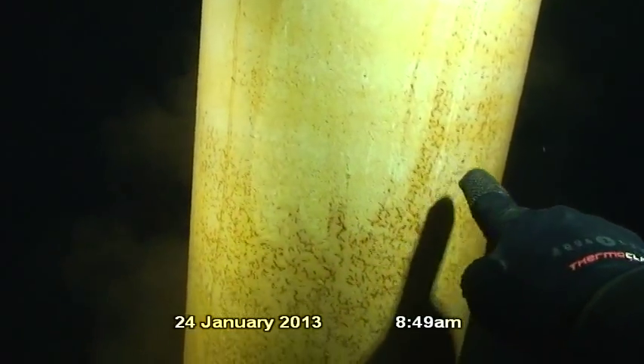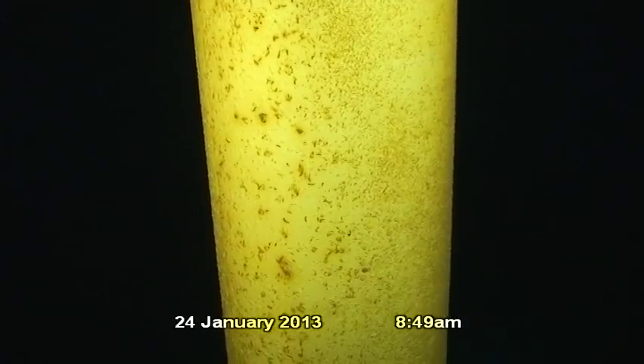The coating is losing flexibility, cracking, and delaminating in many areas on the center pole in this location. The corrosion that was observed on the center pole is very similar to the corrosion that was documented on the vertical walls on the interior of the facility. The coating is losing flexibility and cracking in many small areas, resulting in many areas of light surface corrosion.